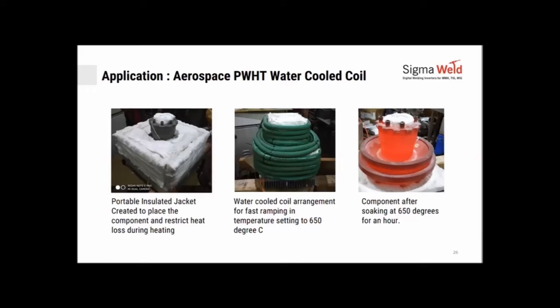Another very critical application for aerospace right now happening. This material here is non-magnetic and also has a very typical challenge where it needs to jump from 650 to 850 under 2 minutes. Otherwise, the heat treatment won't be correct, or it will not reach its desired solution. The way to do this was in two parts. So we built a portable oven around the job itself. We wound the water cooled coil and preheat it up to 650 degrees and hold it there for an hour. Entire job is at 650.